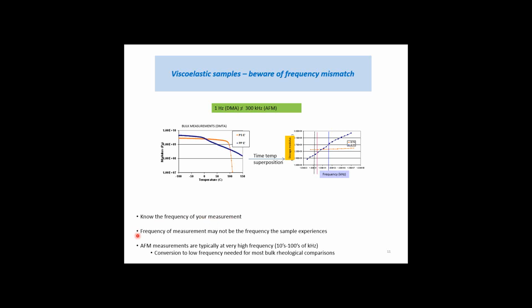The second complication here in AFM measurements is that the frequency that you're doing the measurement at may not be the frequency that the sample experiences. This is especially true for tapping mode and force spectroscopy measurements, where the sample is most likely experiencing the frequency of your measurement plus higher order harmonics. So when you're trying to compare it to a measurement done at a single frequency, it's not clear that that comparison can be done. So just be careful about that.